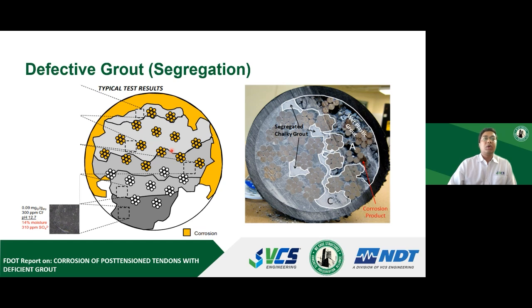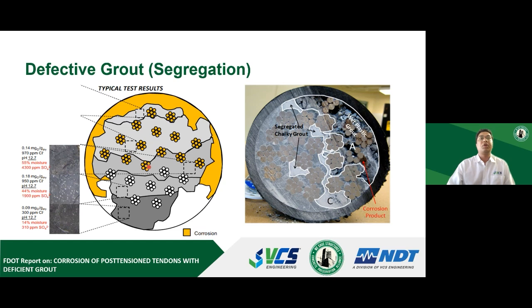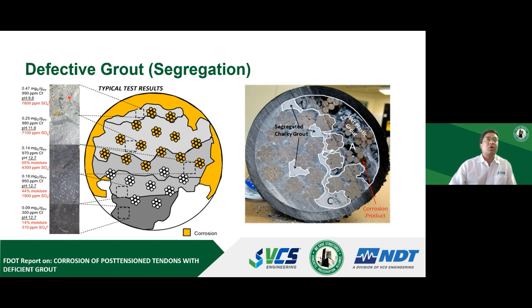Sometimes, when you have high amounts of water in the grout, that can result in segregation, where the heavier cement particles tend to settle down and consolidate first, which results in bleed water on the top layers. As you keep consolidating or curing the grout, it keeps pushing the bleed water up and you have an increasing water to cement ratio. As a consequence, you tend to see higher levels of contaminants or deleterious species like chlorides or sulfates towards the top because of the excessive amount of water or higher water to cement ratios.